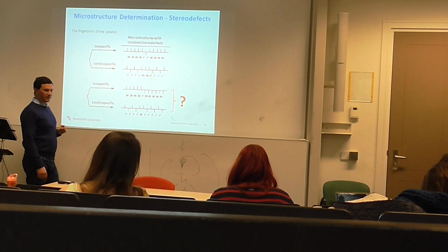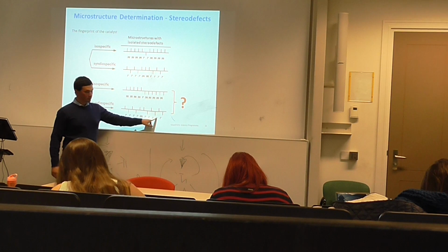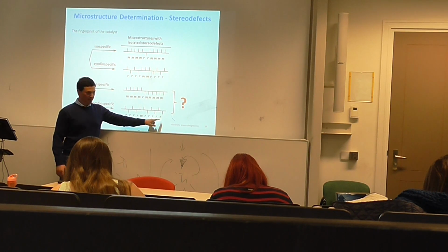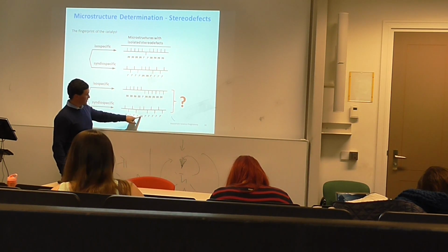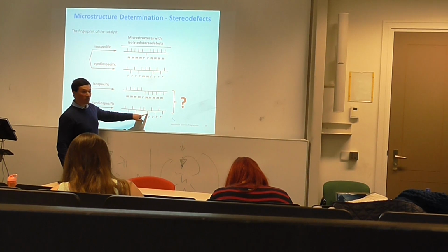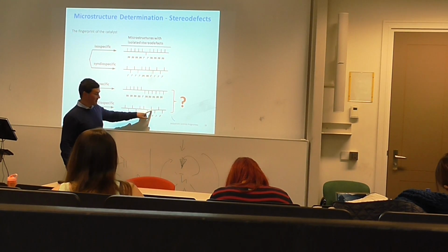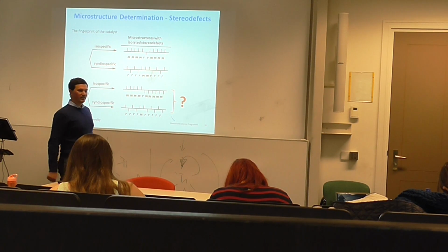Another example for the syndiotactic polypropylene. This is a string of R. Okay? So syndiotactic. It makes a mistake. So M pointing in the same direction. And then it does not correct itself, the site. And it changed the configuration.